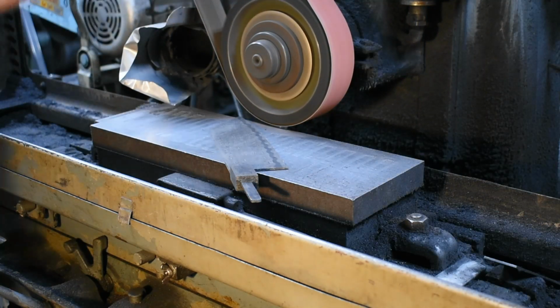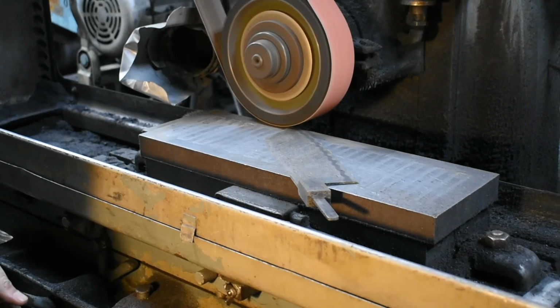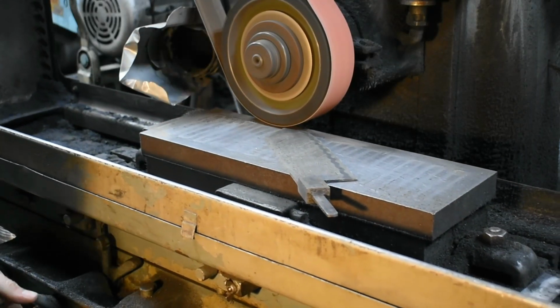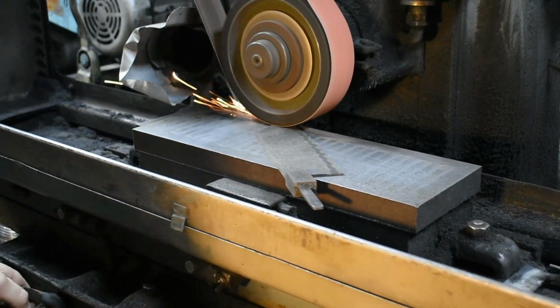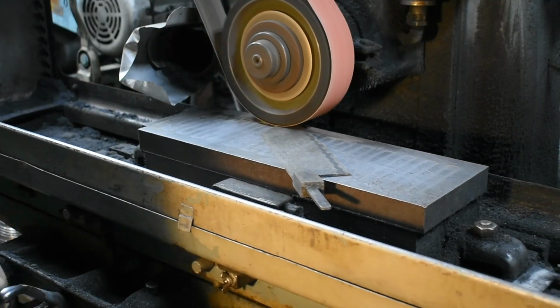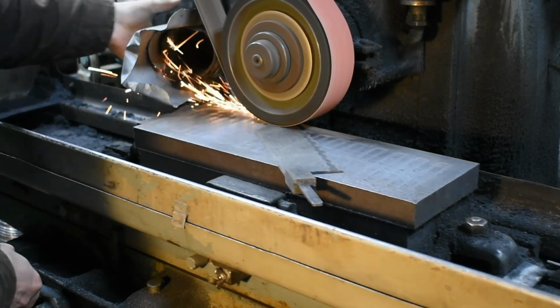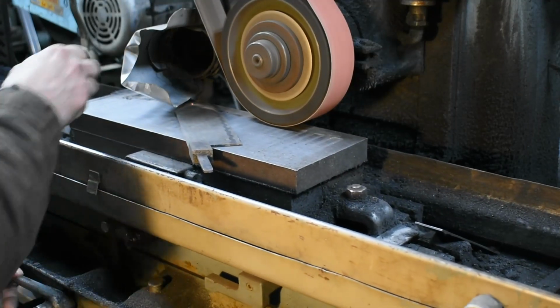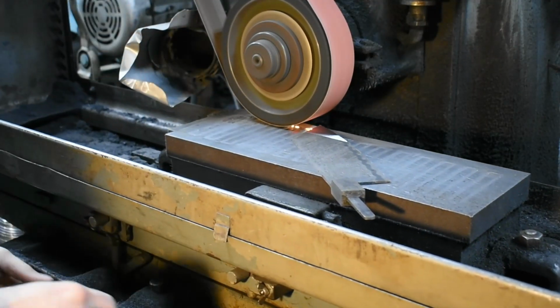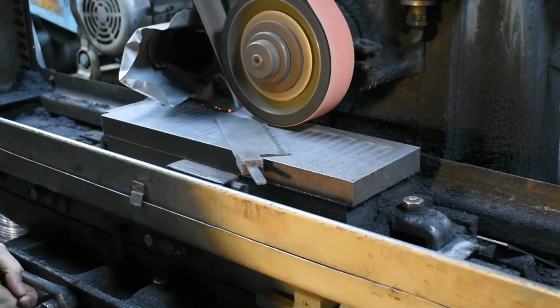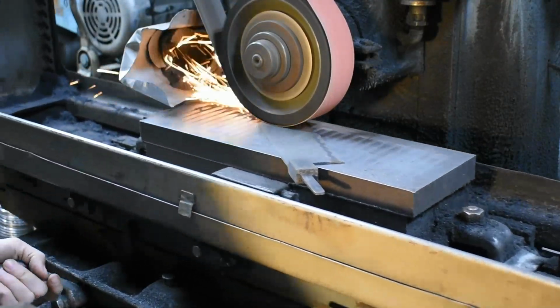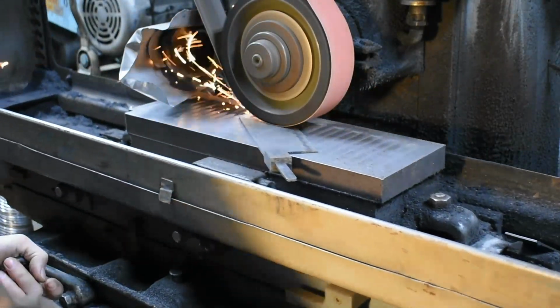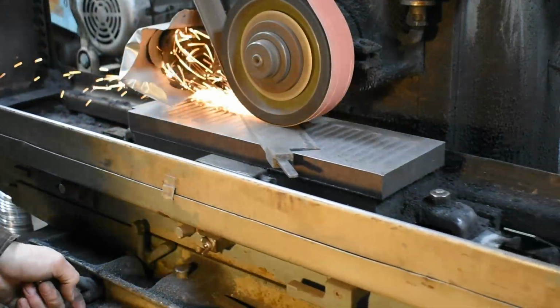Surface grinder time. Of course, we're back here at the old Abrasive 3B surface grinder. I got a 120 grit ceramic belt on there. And I'm going to take 5/1000ths of an inch off each side, which in my experience is enough to get through the decarb layer and give me a decent surface finish to get an accurate Rockwell test.